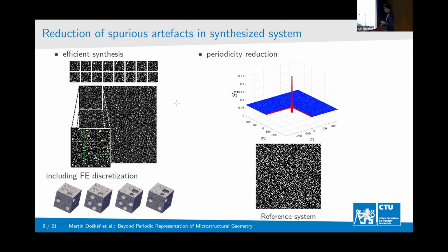So those are the three methods how to design the compressed representation, as I said. Then you have a set of your tiles, and you can very efficiently, as you can imagine, just putting images side by side, generate some new realizations of your microstructures. But also, if you have a finite element tool that is capable of creating finite element meshes that are topologically and geometrically compatible across the right sides with the same code, you can discretize only the compressed representation and then create finite element meshes for the new realization just by again stacking together different finite element meshes.